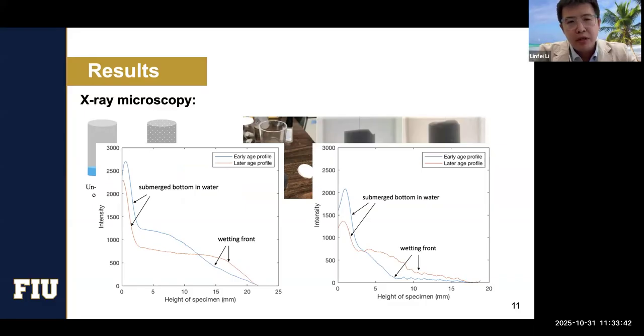From the left-hand side, it's just the untreated sample. On the right-hand side, it's an injected sample. As you can see, there is a clear trend, with the intensity significantly dropped. And based on the derivation of that, we'll also be able to target the wetting front. So from the X-ray microscopy, it's kind of an indirectly proved concept: the nanoparticles are successfully injected, and they make the microstructure denser. Oh, one more thing, for the early age profile and later age profile: for early age, we started scanning immediately, but for later age, every time you run the test it takes about 3 hours, so we just ran 2 tests.